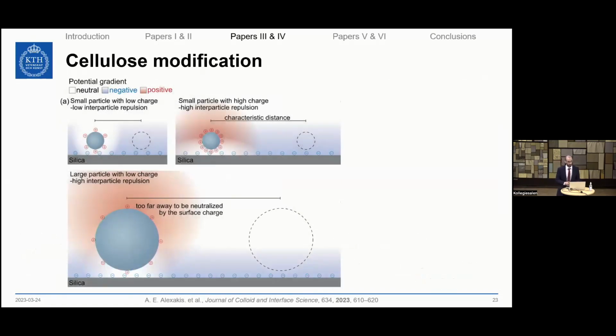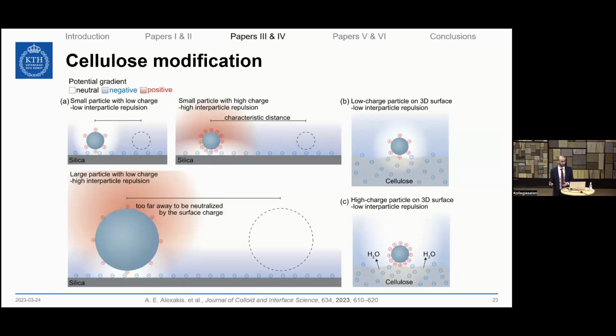In other words, in the case of silica, when we have a charged particle that sits on that surface, if that particle has low charge density, this means that the nanoparticles can sit closer together, so further optimizing their adsorption. Whereas the opposite happens when we have a nanoparticle with higher charge density or a really big nanoparticle. In the case of cellulose, we have what is called the volumetric distribution of charges on that surface. So when we have a particle that sits on that surface and it is charged, it can reach the charges that are further and deeper down into that cellulose surface. And cellulose, because it tries to compensate the charges of that adsorbed moiety, in some extreme cases, if the nanoparticle is highly charged, it can lead to the deswelling of the cellulose, which we have also monitored in this study.